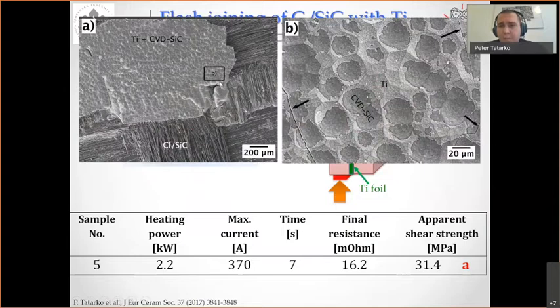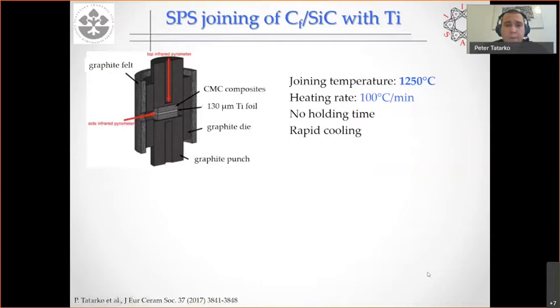Here is just an example of the fracture surfaces. Here I would like to point out the conformal behavior of titanium. This layer, which was of course peeled off at some places, you can see how nicely it conformed to the rough surface of the CMCs. So this is a very nice result as well, and that's the reason, because it conformed very well. It got nice integration with the matrix. That's why we could get such a high apparent shear strength.